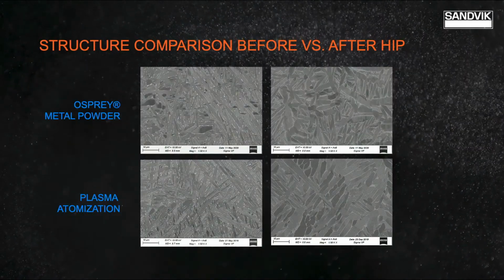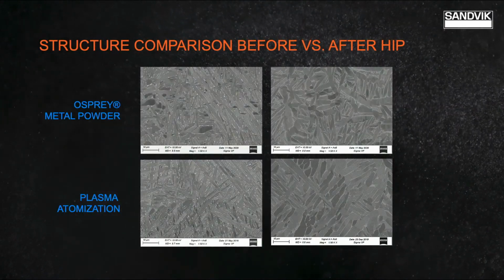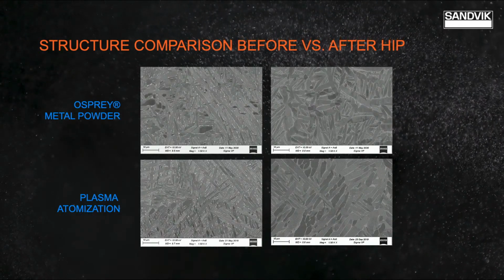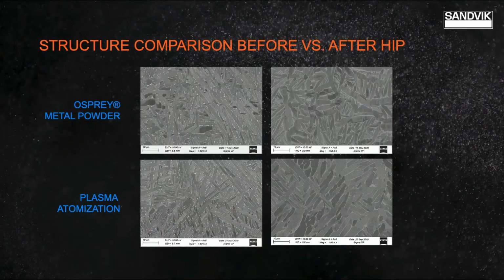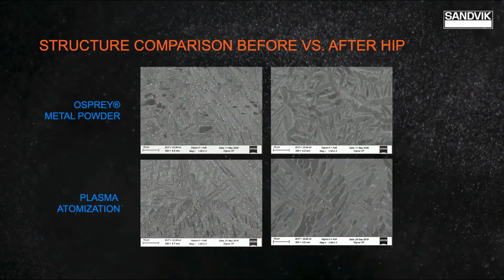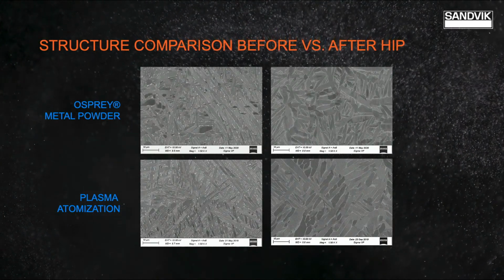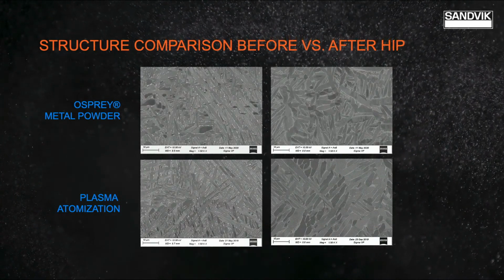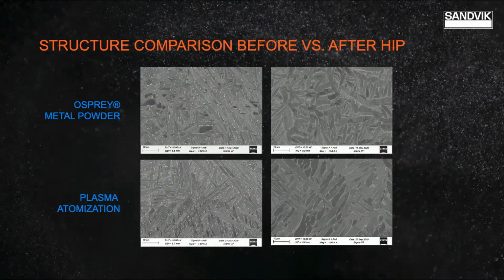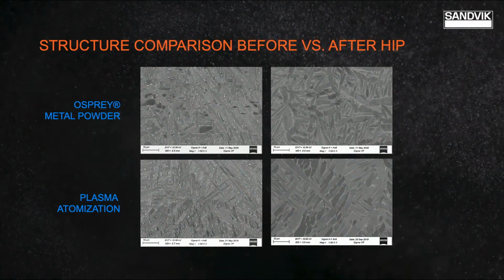Okay, I understand now, but what can we tell about our microstructure when we compare it with other atomization methods out there? Wow, that is an important question. And as you can see on the slide, I placed on the top the microstructure that was obtained for the print done with the Osprey titanium powder, obtained after stress relief and also the heat treatment. And besides some slight coarsening of the phases, these microstructures are very well in line with what we expect for this alloy.